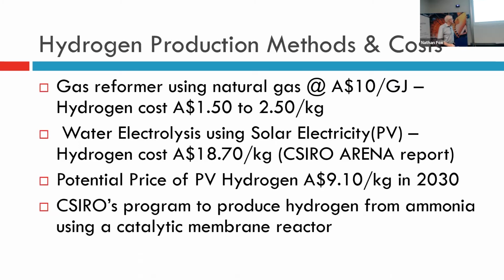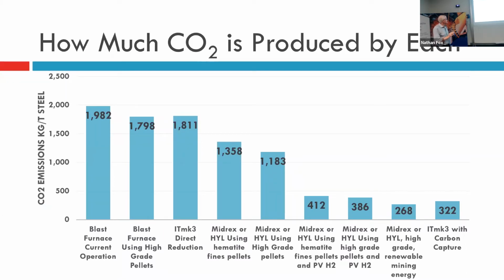This is a graph that shows how much CO2 is produced by each of those iron production methods. And this is a blast furnace, which produces about 2,000 kilograms of CO2 per ton of steel. If you use high-grade pellets rather than the standard 58 to 62% iron ore, then you can make a reduction of about 10 to 15%. And I see that as low-hanging fruit. All the iron producers should be able to produce iron and steel using less CO2 than they're doing now, because they're using fairly low-grade iron ores. In the early days of the Pilbara, the grades were much higher, but they're not that high these days.